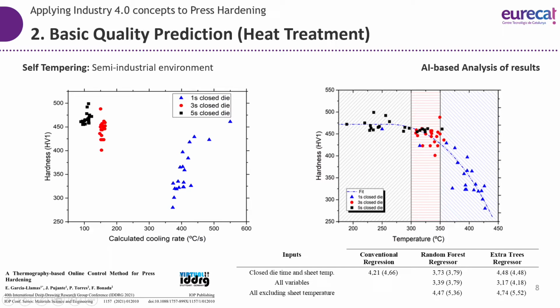And this is because we are opening the die with a final temperature, so when we open the die, the temperature of the sheet metal is hotter than we would want. In retrospect, it makes sense. But the thing is that we could do these experiments. We saw definitely that self-tempering was an issue.